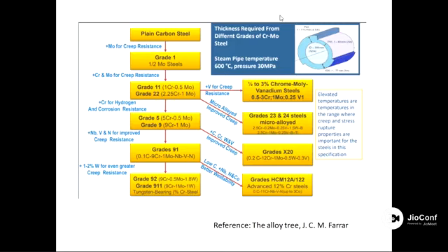On the top left, you would see a picture of a steam pipe, which could be used for 600 degrees Celsius with pressure around 30 megapascal, right? So this kind of power pipe or steam pipe, what is the idea of showing this picture? If you manufacture this pipe for this application with, say, P22 material, then the thickness is going to be around, say, 150 millimeter. But for the same parameters, with X20 material, the thickness could be around, say, 77 millimeter. So there is some reduction in thickness. This is X20 material with the addition of carbon, chromium, tungsten, and vanadium.